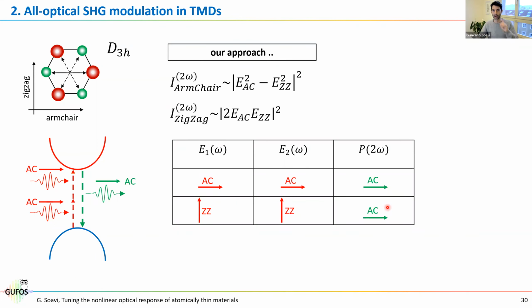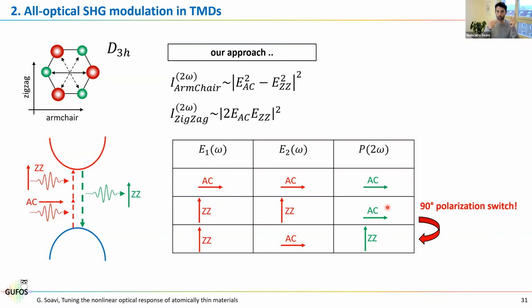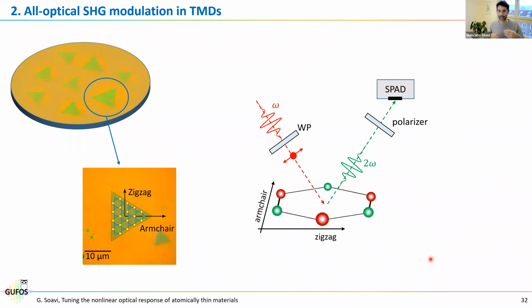So you see that it doesn't matter, you go along 0 or along 90, you always emit a second harmonic along armchair. However, if you now split your two photons into two pulses, one along armchair, one along zigzag, then this difference will go to 0 and everything will be emitted along the zigzag direction. So basically, you can switch the polarization of your second harmonic by 90 degrees. And now, let me show you how we can do that. So first of all, we were working in this case with CVD grown materials because it was easier to find the armchair and the zigzag directions.